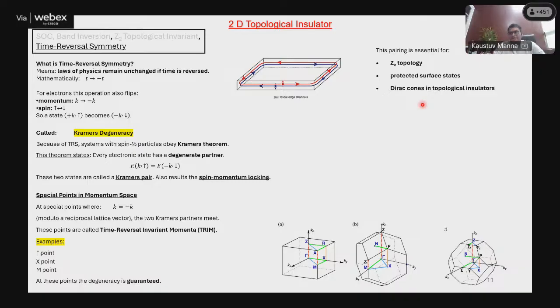Now, if you put together the Z2 topology and the protected surface state, what it gives rise to is spin momentum locking. In the 2D topological insulator, the edge state always has one spin channel because of the up spin, and another spin channel because of the down spin. So if you want to observe the time reversal symmetry protection, there is no magnetic field. The magnetic field is replaced by the internal magnetic field, which has already played its role by introducing the band inversion. And because of that, we have got Z2 topology and time reversal symmetry.